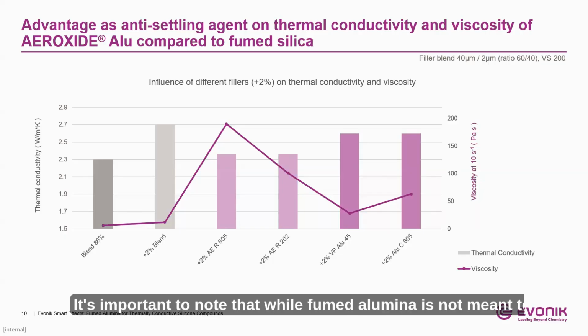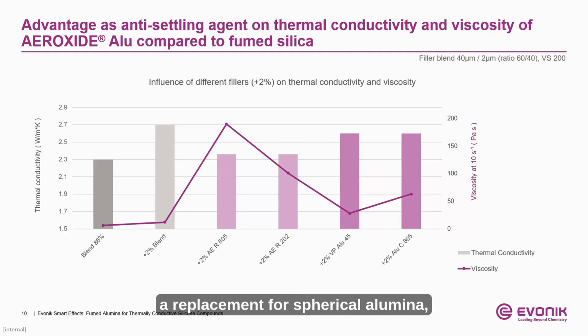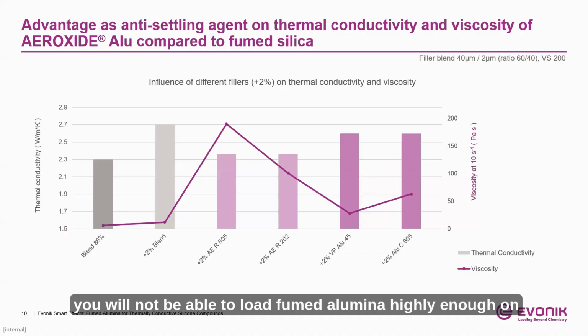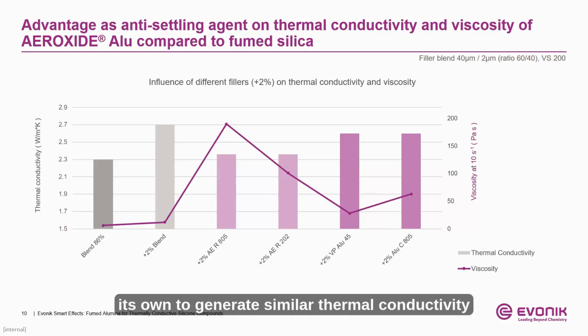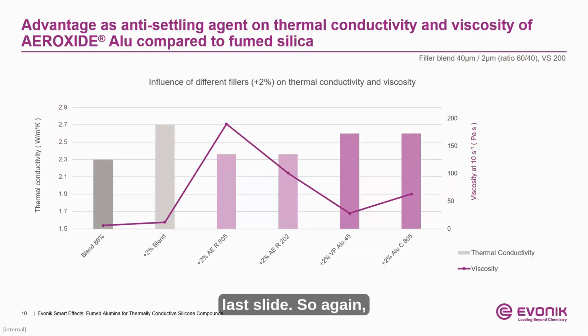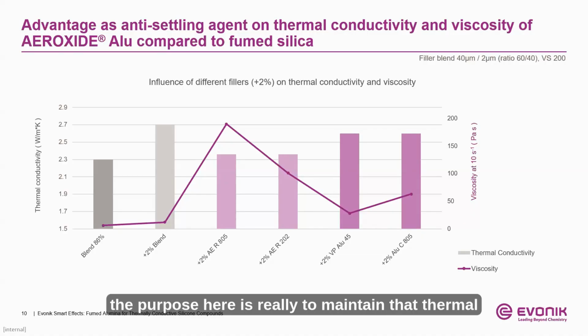It's important to note that while fumed alumina is not meant to be a replacement for spherical alumina, you will not be able to load fumed alumina highly enough on its own to generate similar thermal conductivity values while maintaining a workable viscosity. The benefit is that it will maintain the overall thermal conductivity of the system, despite its use in conjunction with the anti-sedimentation benefits we've seen on the last slide. So again, the purpose here is really to maintain that thermal conductivity while functioning as a suspension control agent.